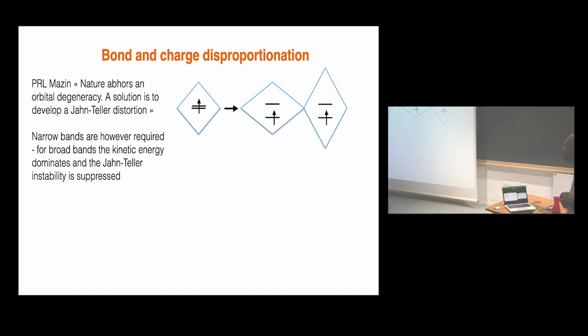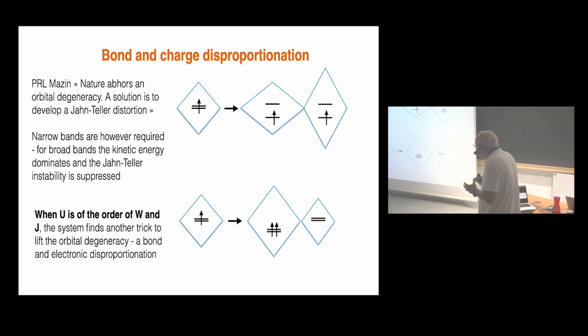So the proposition of Igor Mazin and co-workers is that when the on-site repulsion energy is of the order of W and the Hund's coupling J, the system finds another trick to lift the degeneracy. And this trick is to go to this breathing mode. So at high temperature, you have a single octahedra size, but when you transition, you go to this breathing mode, and one of the octahedra becomes larger. This is a long bond, and the other a short bond. And obviously, when you do this, you change the energy of these levels. And in the extreme case, you would transfer the two electrons on one side, lifting the degeneracy.